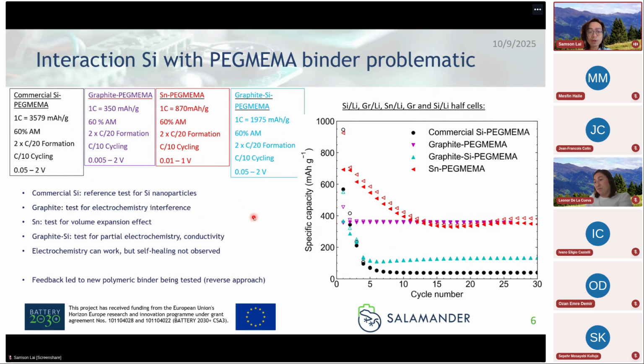Silicon has this alloying ability, it creates cracks and volume expansion. So let's test another material, tin, which also has volume expansion, but maybe it's that, and can we isolate that? And we actually got a pretty normal curve of what you would expect for tin in terms of performance. So you get this gradual degradation, and then you kind of get a low spot, and then onward. And so that kind of explains that it wasn't the volume expansion, because this sort of is working there.